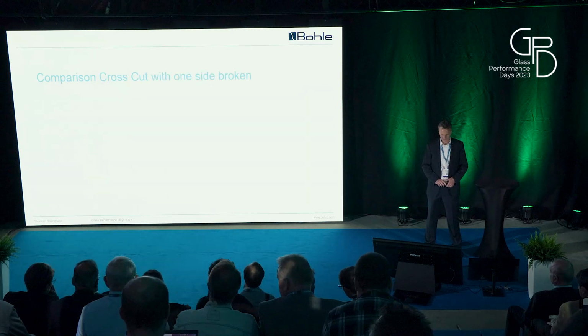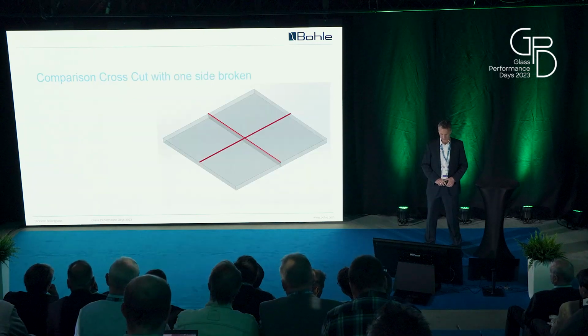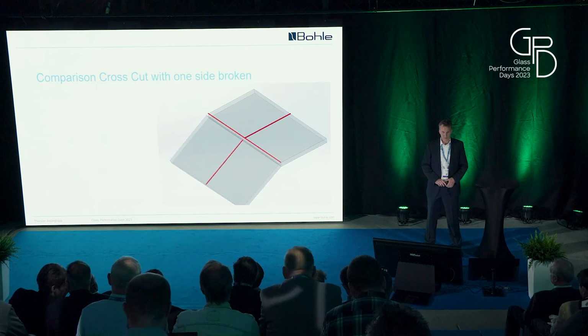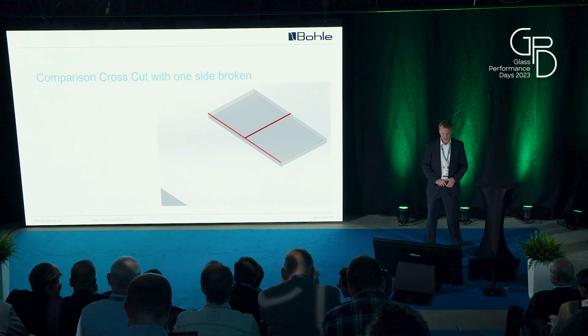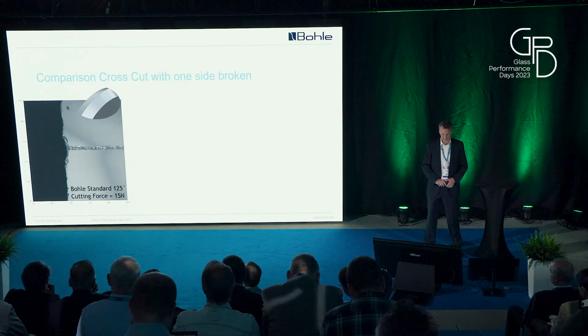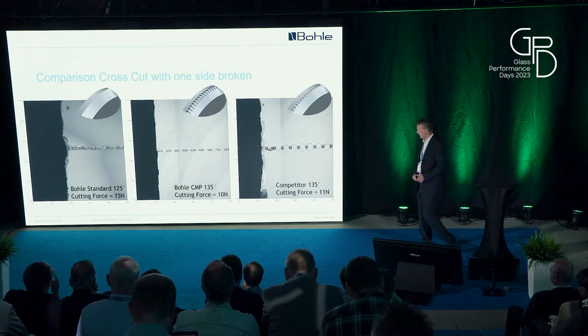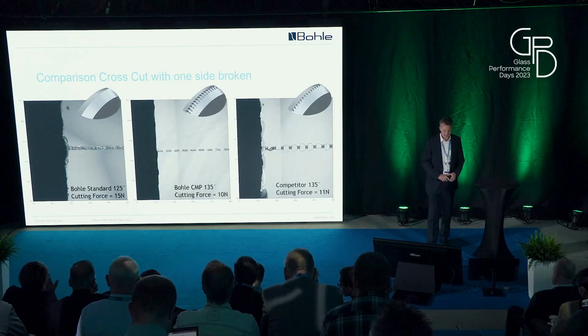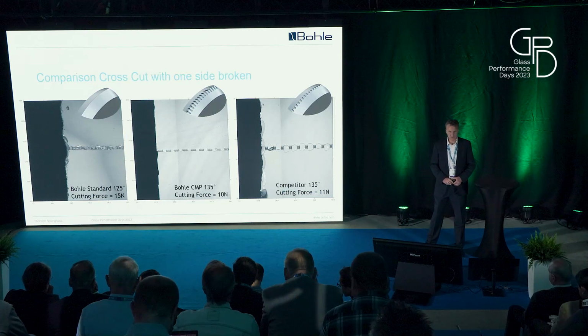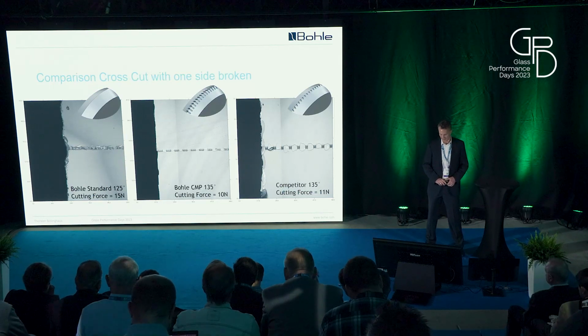And also when you break the glass, when you take the cross cut and you break it, you will see what you then expect from the picture before. You see that on the left side, the classical cut is a little eaten. You see the very nice picture of the recessed cutting edge, and you see that the cutting edge that is not continuous doesn't give the same result.